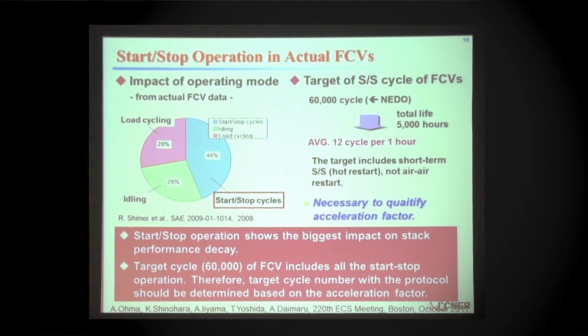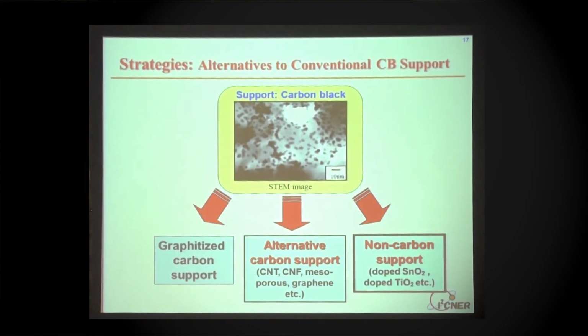For several years, automotive companies have made many demonstration programs, and through these projects they have learned what the decisive degradation mechanism is, which shows the degradation of fuel cell vehicle performance. That is the slide presented by, I think, Nissan and group. They have clearly shown that start and stop cycling causes almost half of the degradation of fuel cell vehicles. Therefore, NEDO has set the target that 60,000 cycles up to the higher voltage must be survived, and that corresponds to the lifetime of fuel cell vehicles. And therefore, we have started to work on the electrocatalyst issue, and we want to solve such a problem.